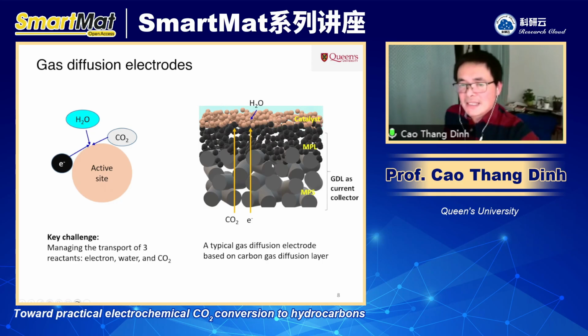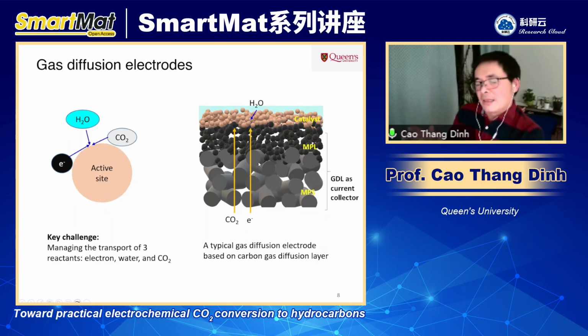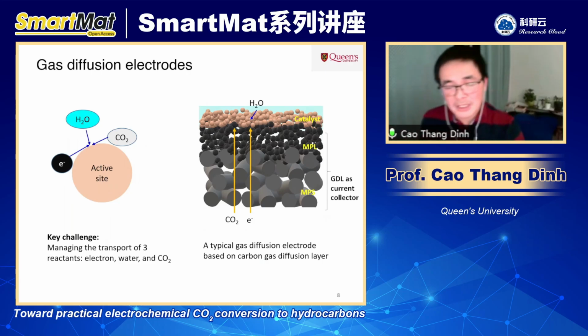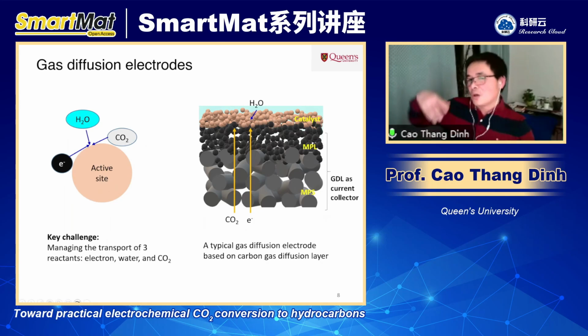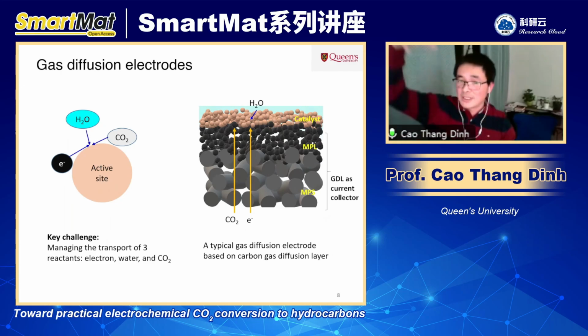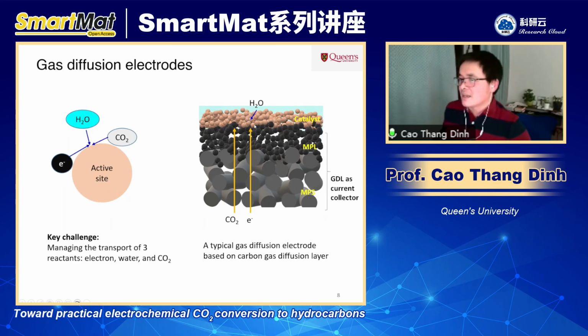So on the right-hand side here, I'm showing a porous gas diffusion layer, often a hydrophobic one, and it's conductive. And then you deposit the catalyst on top of that, right? The gas diffusion layers are often made of carbon particles, and then you combine them with a hydrophobic polymer like PTFE. So you mix carbon, which is conductive, with PTFE, which is hydrophobic, and combine them together to make a porous, conductive, and hydrophobic layer. The hydrophobicity of this layer will prevent the water from penetrating. It allows only CO2 to go through, right? So CO2 goes through this porous layer, water comes from the liquid, and all of them meet on the surface of the catalyst layer. So that works perfectly, right? We bring three components together.